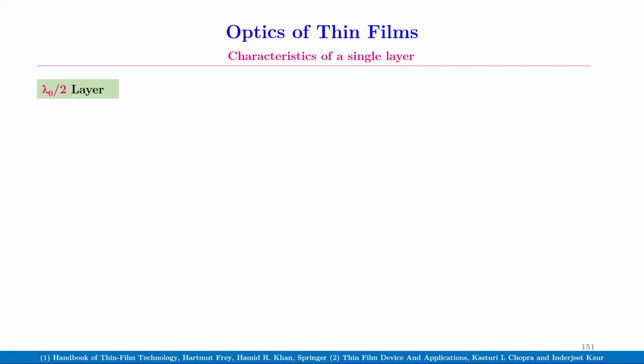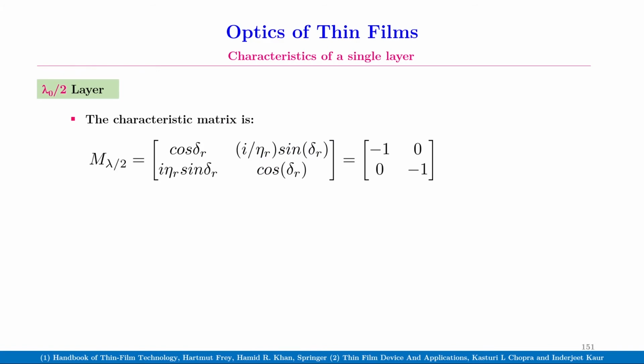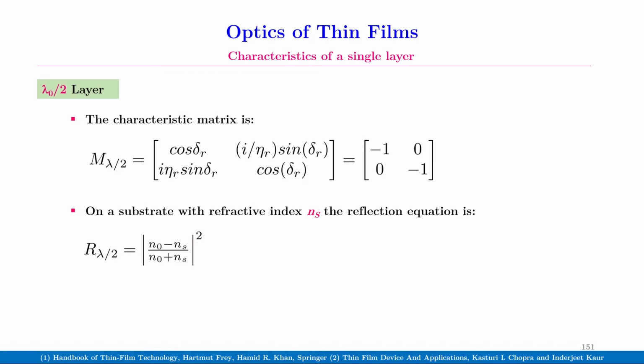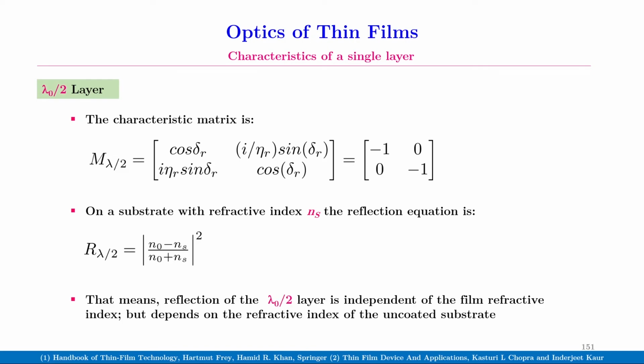We will now discuss thin films having a thickness equal to λ0 divided by 2. In this case, the characteristic matrix M(λ/2) turns out to be the matrix [−1, 0; 0, −1]. On a substrate with a refractive index ns, the reflection equation turns out to be R(λ/2) equal to modulus of (n0 − ns) over (n0 + ns), the whole square. That means reflection of the λ0/2 layer is independent of the film refractive index, that is n1, but depends on the refractive index of the uncoated substrate.